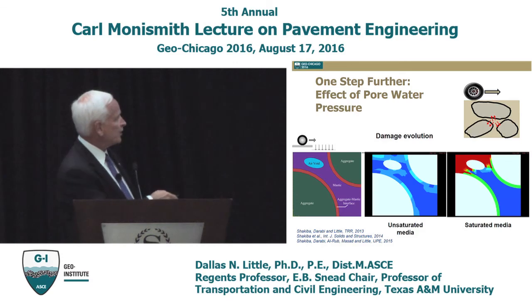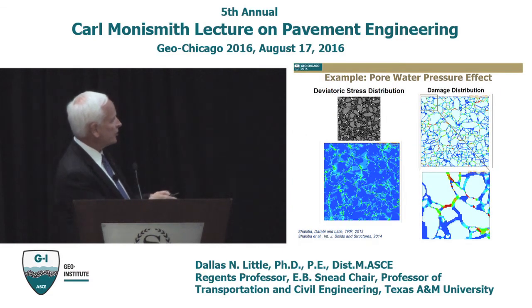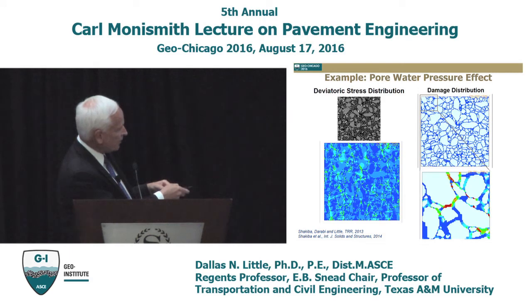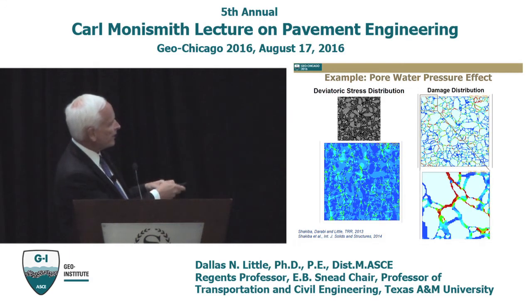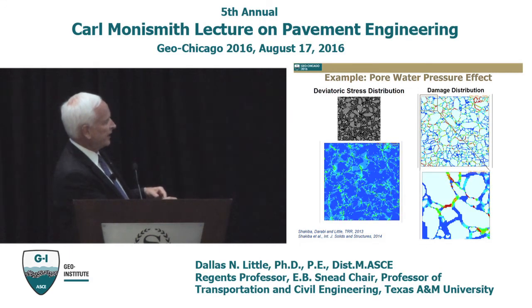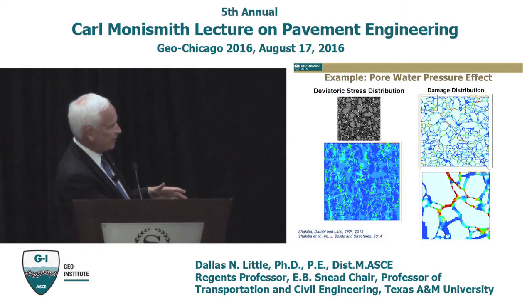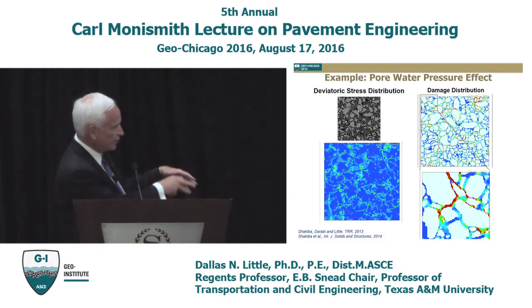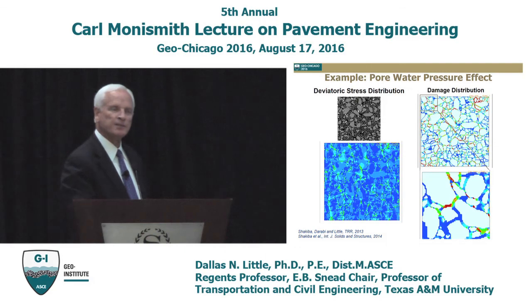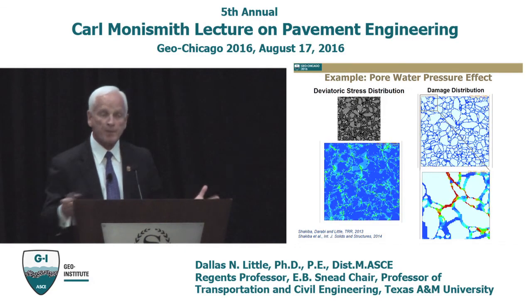And here's another view of a similar type of situation. What we're doing here is we're looking at the damage process. We're blowing up this little section here in this micromechanical analysis, and the hotter colors represent the damage areas, so you can see that damage is occurring at that interface in most situations, which would cause stripping.